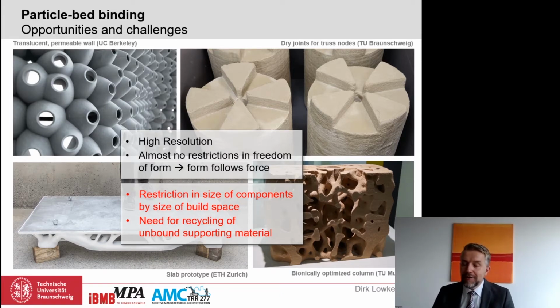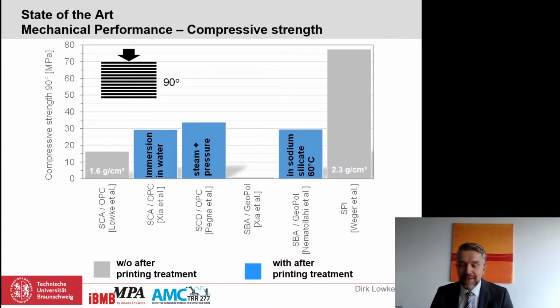Okay, let's move on now to the mechanical performance. For selective cement activation, the strength values without after-printing treatment do not exceed 17 megapascal. If an after-printing treatment is applied, you can see this here in the blue columns, then strength values can reach up to 34 megapascal. The level of strength is within the expected range, as these concretes have a density of approximately 1.6 gram per cubic centimeter, and therefore they can be classified as lightweight concretes.